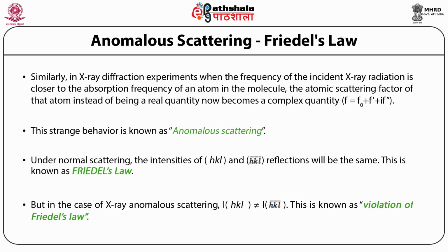Under normal scattering, we will later prove that the intensities of the HKL reflection and the H bar, K bar, L bar, or minus H, minus K, minus L reflections will be the same. That is, intensity of HKL will be equal to intensity of H bar, K bar, L bar. This is known as Friedel's law. But in the case of X-ray anomalous scattering, intensity of HKL will not be equal to intensity of H bar, K bar, L bar, and this is known as violation of Friedel's law.